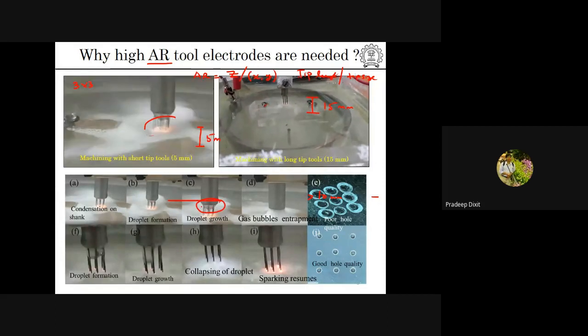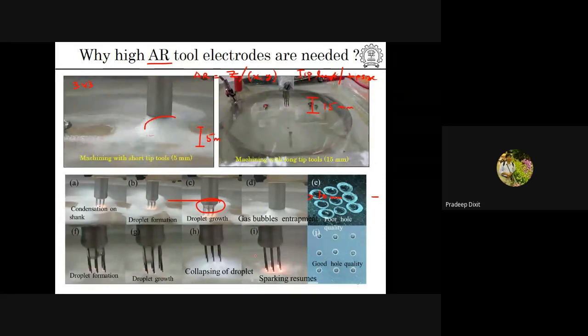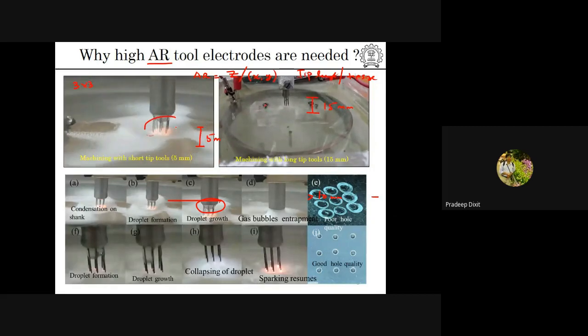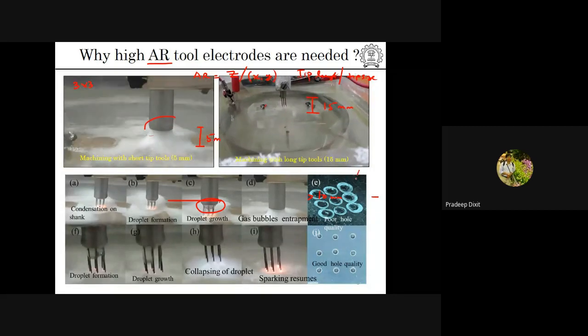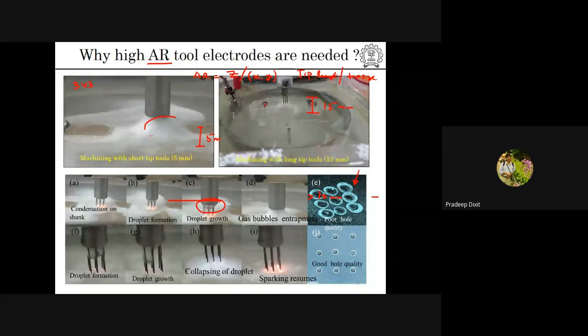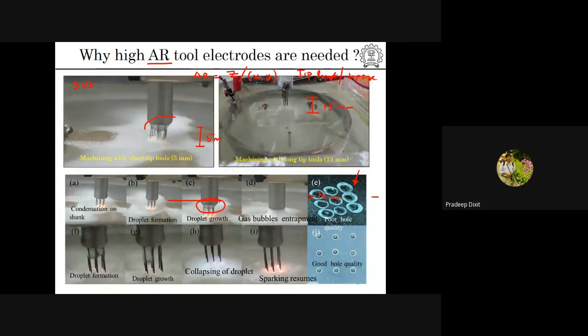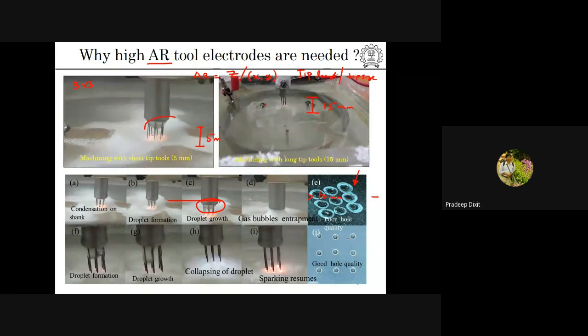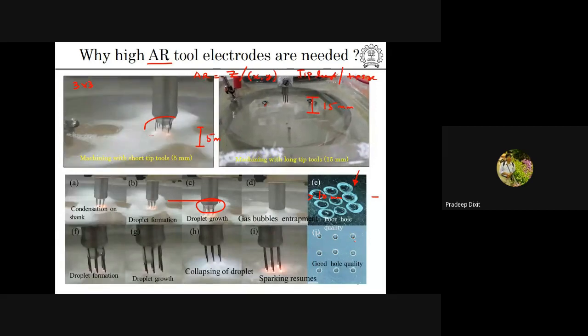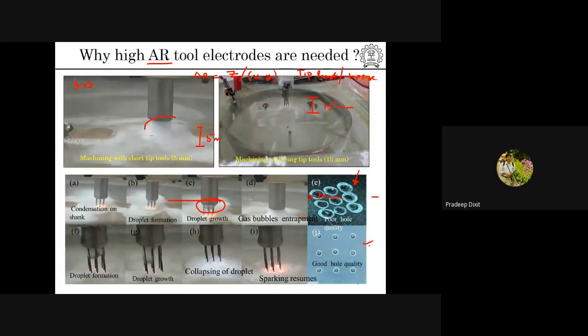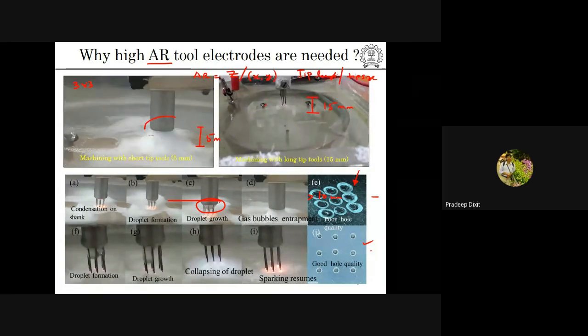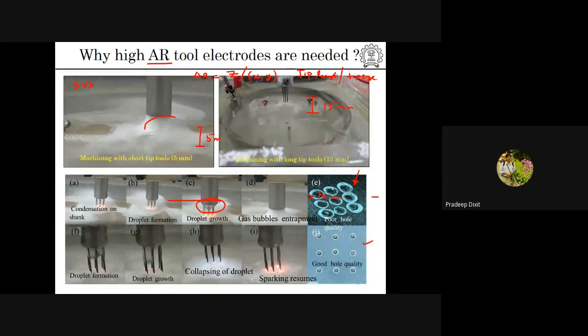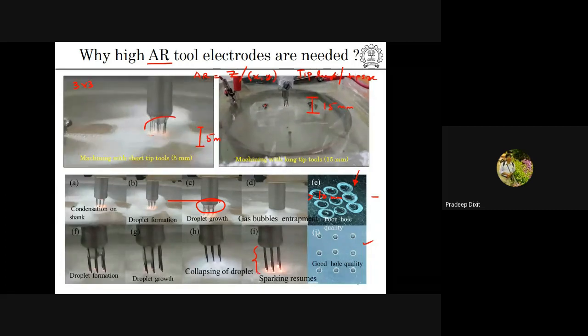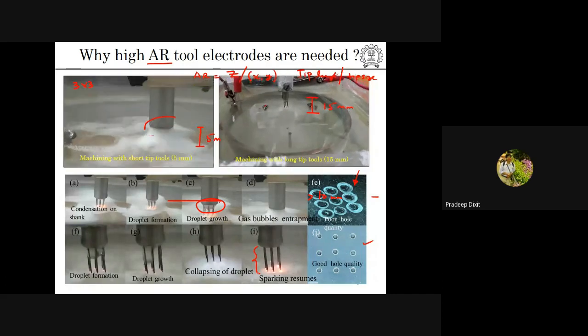Okay, so this is this kind of bubble phenomena. If you use this 5 millimeter or shorter tip, the through holes which are formed are not nice. There is a lot of overcut. But if you carry out with longer tips, you will see that they all still have some kind of overcut, but the overcut has been drastically reduced. So these pictures clearly indicate that if you want to create an area array or a large number of through holes at the same time, you have to use a tool electrode which has a very long edge here.